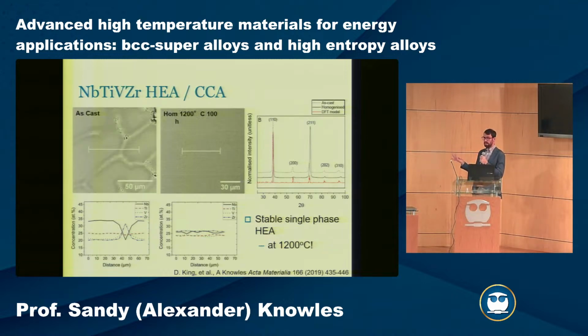So we melted up a series of alloys, and then we looked at them both in the as-cast condition and then after thermal annealing. For us, this is a marked response: at 1200, there is truly a single phase field, so it is actually a high entropy alloy in that you can get to this single phase solid solution, which is one of the key characteristics of some of the high entropy alloys. We then characterize it in terms of crystal structure, BCC, what lattice parameters, as well as what composition we actually produced.